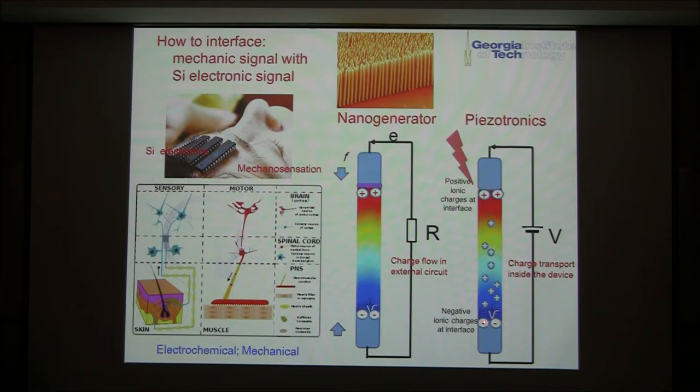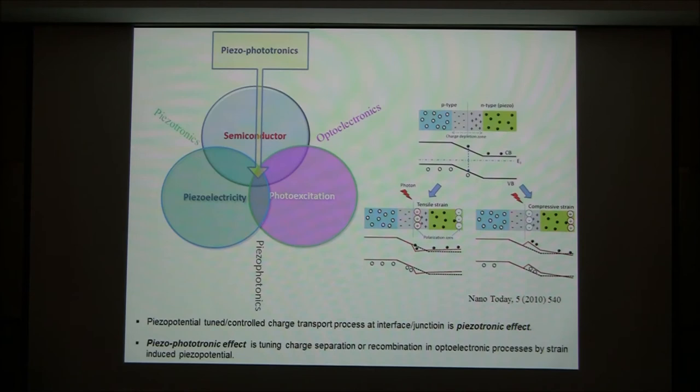This voltage drives the transport of the carrier here, but the presence of the polar charge can greatly control the way the carrier flows through the interface. This is the core of Piezotronics. Mechanical agitation produces piezoelectric charge to tune the carrier transport process — this is the fundamental of Piezotronics.